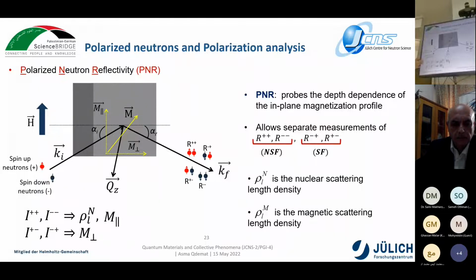For the setup of this technique, we have an applied magnetic field in this direction, and then an incident neutron, either aligned parallel or anti-parallel to the magnetic field, so spin down and spin up neutrons directed toward the sample surface with an incident angle alpha i. With fully polarized neutrons, we can measure the four scattering cross sections. The non-spin-flip ones, R++ and R--, are sensitive to the magnetization component parallel to the magnetic field, while the spin-flip scattering cross sections, R+- and R-+, are sensitive to the magnetization component perpendicular to the magnetic field.